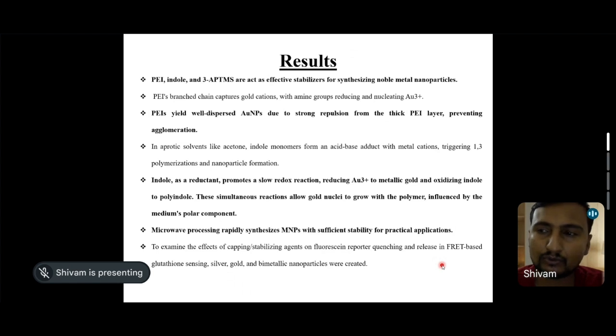But one day, fortunately, I tried the kitchen microwave oven to produce a large amount of highly reduced nanoparticles in a very short time. After exposure to microwave, the gold metal cation converted into nanoparticles within 30 seconds with a very good efficiency of reduction. So this point is also important to note: how microwave processing influences the reduction process and speeds up the reaction kinetics in the conversion to nanoparticles.